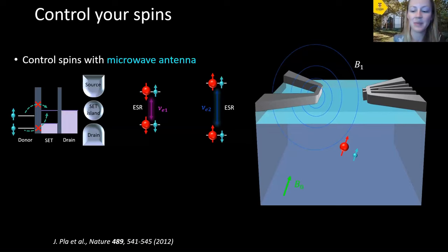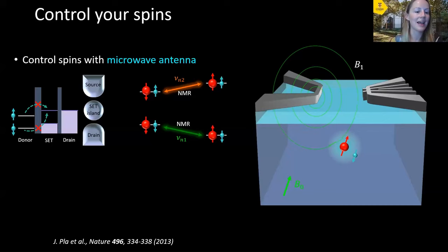We can also do the same controlling experiment on our nuclear spins using the same on-chip microwave antenna. We just have to apply different frequencies. These frequencies are much lower than our electron spin resonances, and we obtain two nuclear magnetic resonance peaks corresponding to the electron either being spin down or spin up. So this is how we can flip the spins of the nucleus and the electron.